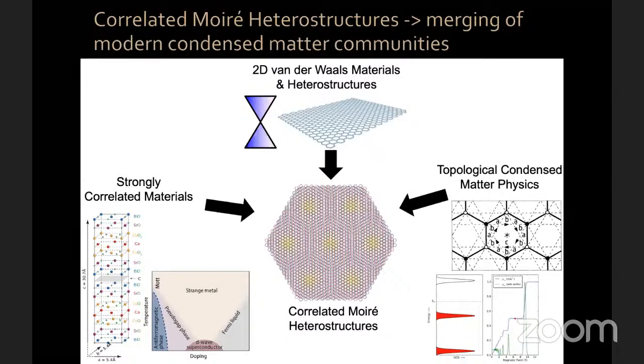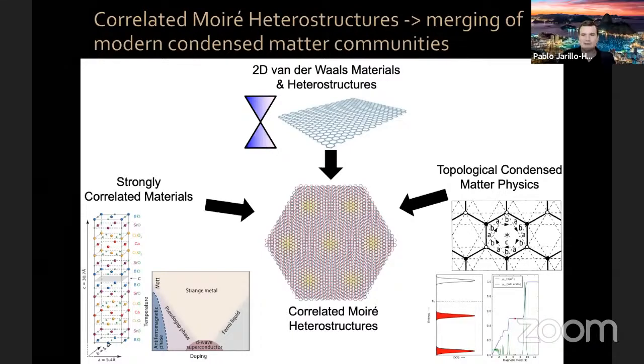But I think I missed something because I understand the ferroelectric phase mechanism, but I missed the driving mechanism for the magnetic phase. Okay, so the magnetism occurs when, first of all, the ferroelectricity is in twisted or in parallel stacked hexagonal boron nitride. You don't need graphene for it. The ferromagnetism has been seen in several Moiré systems. The first one was magic angle graphene, where one of the graphene sheets is aligned to the hexagonal boron nitride lattice underneath it in the substrate.